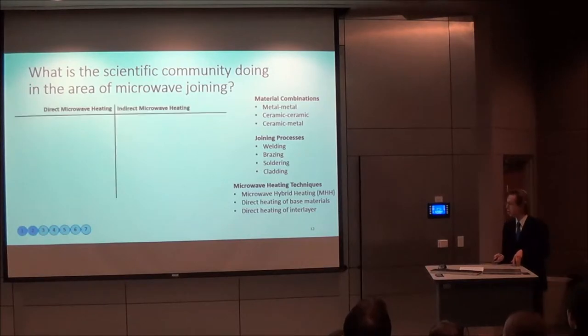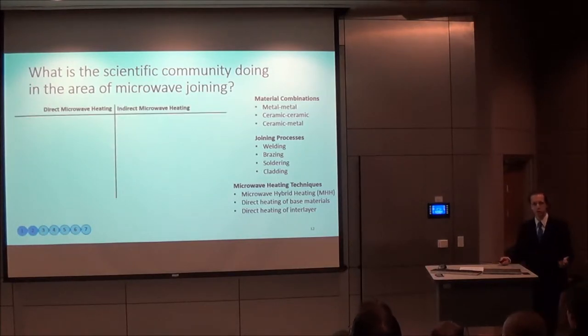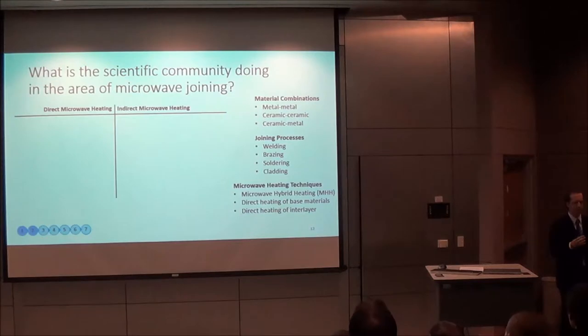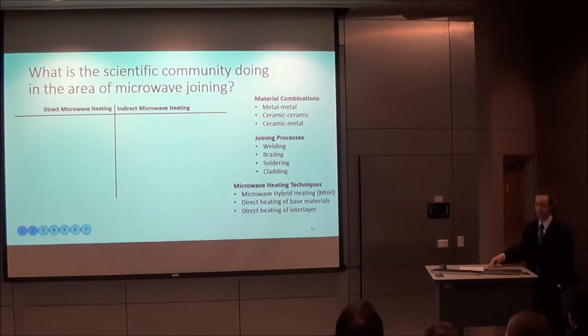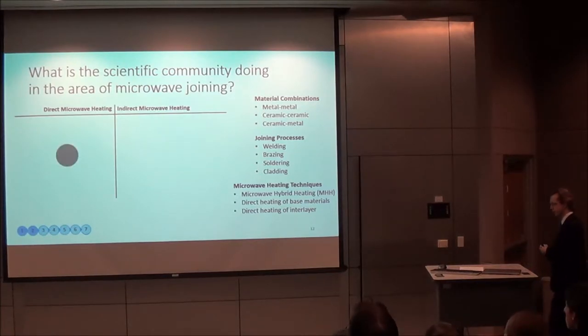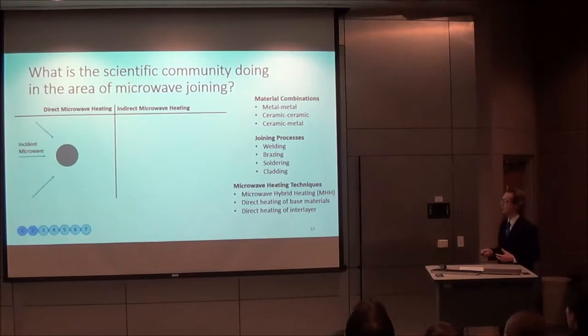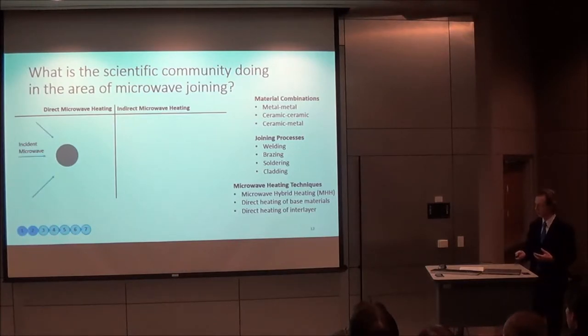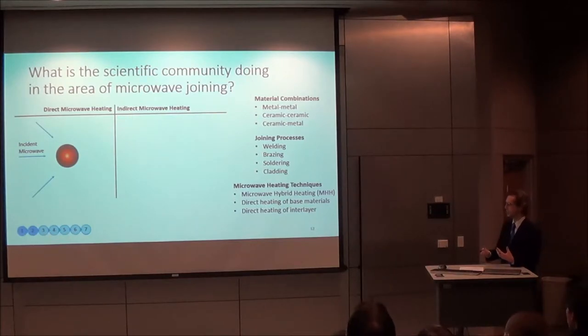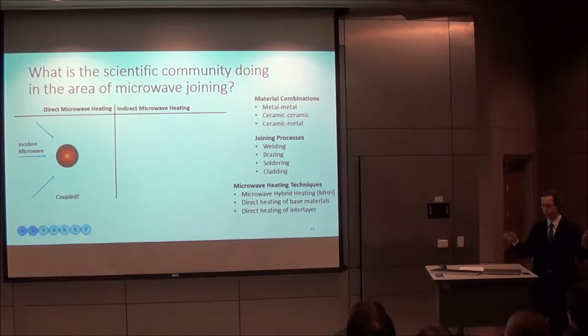And so I think it would be helpful to illustrate the difference between direct and indirect heating, because this really comes down to one of the most important unique advantages of microwave heating. Direct heating happens when, let's say, you have your target, your joint that you want to heat, and the microwave energy reaches it, and it is coupled to the target, it's absorbed, and it heats generally from the inside out. This is what I would call a coupled condition.